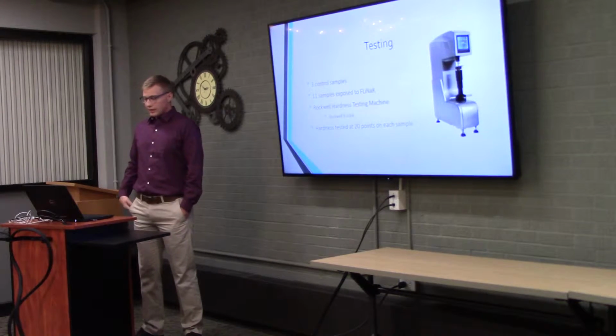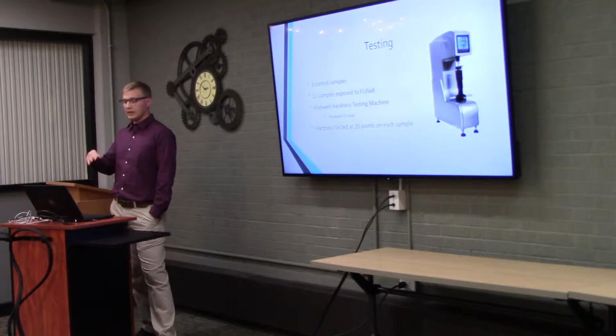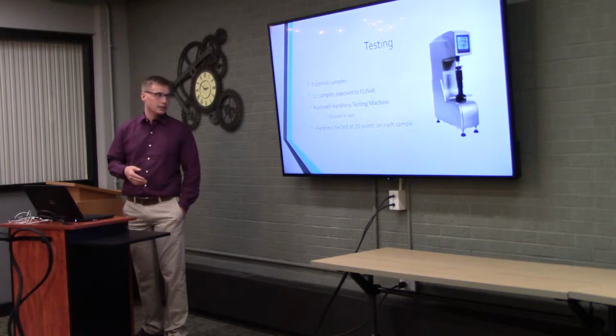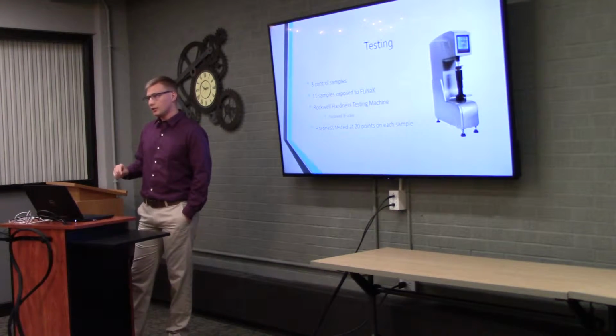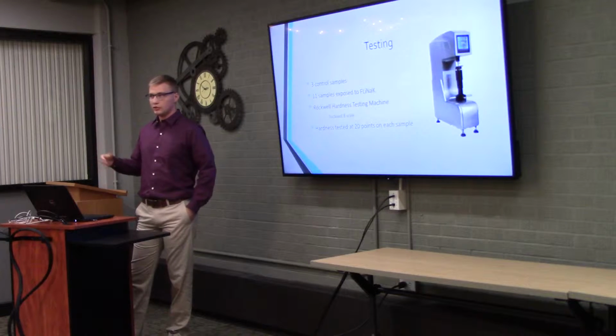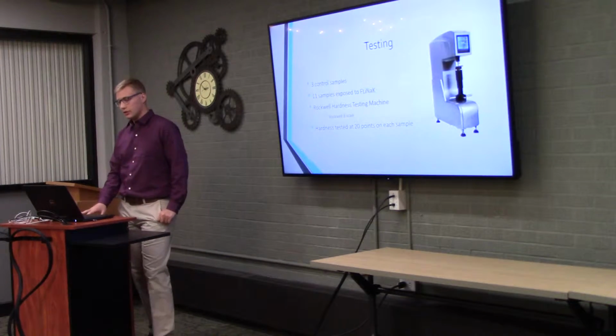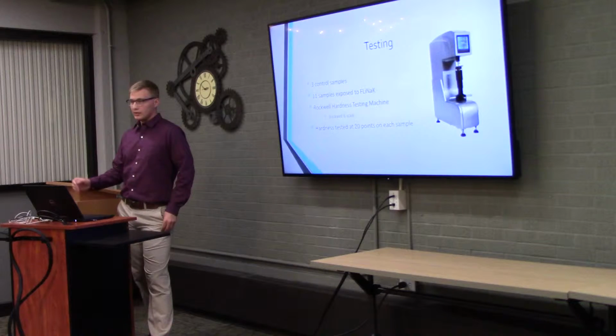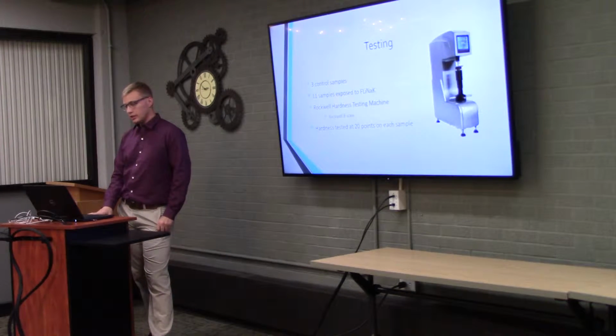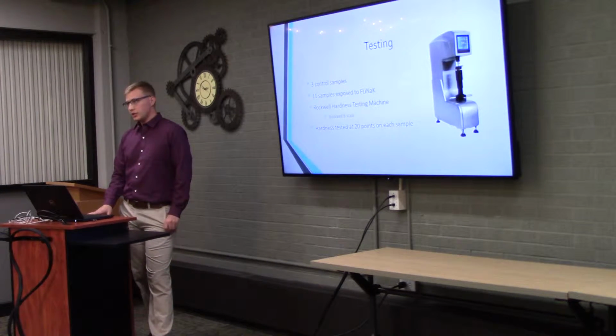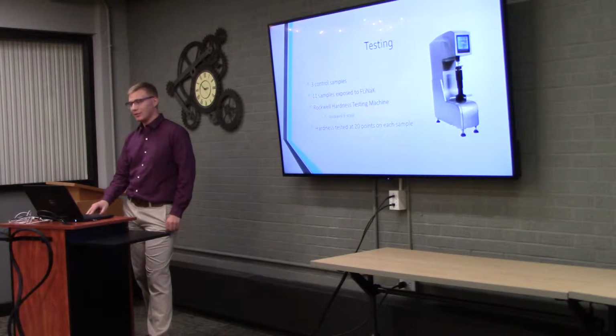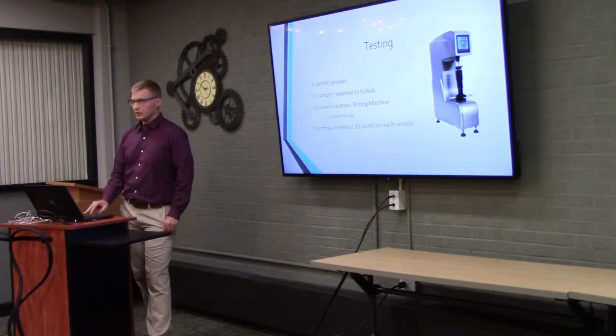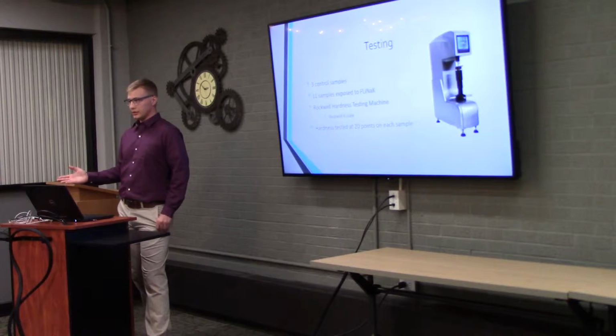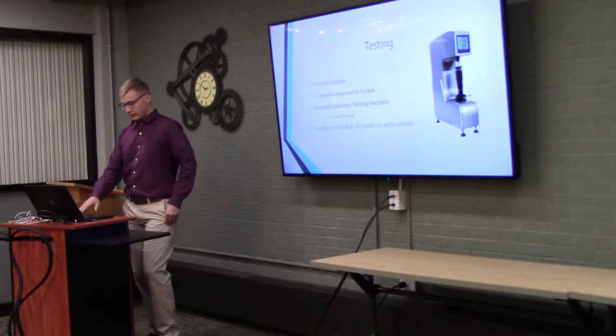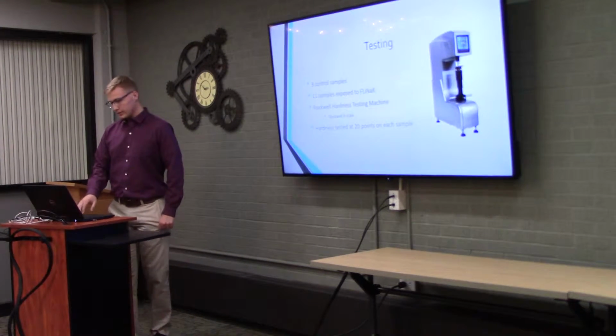So then the testing for this, I tested the 11 samples that I just talked about that were exposed to the FLiNaK. And then I also tested 3 control samples that had no exposure to the salt whatsoever. Tested them on a Rockwell hardness testing machine, which gave me data on the Rockwell B scale, which doesn't have any meaningful units in and of itself. It's mostly just used in comparing the hardness of materials to each other. So it suits the purposes of this project.